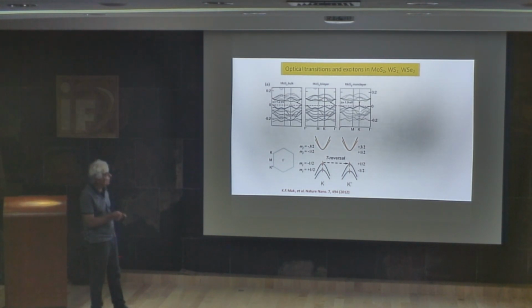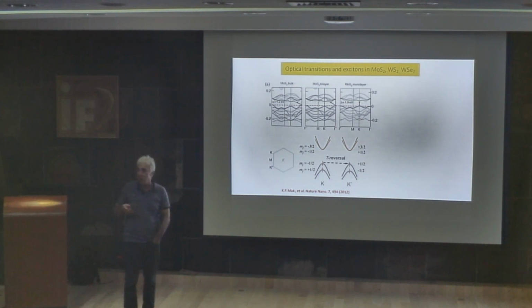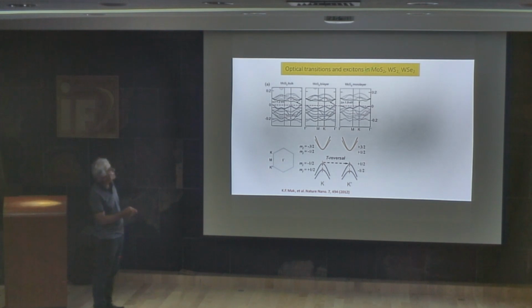This is important. When I have a direct gap, I can have emission of light. This is like the case of those III-V compounds, where the laser is made from those III-V compounds. So when you have a direct gap, you can use it for optics, for light emission. But in MoS2, there are many different interesting things. One is a very strong spin-orbit coupling. The spin-orbit coupling splits, for example, the top of the valence band. Due to the spin-orbit coupling, you have the splitting of this band here, near the K point.